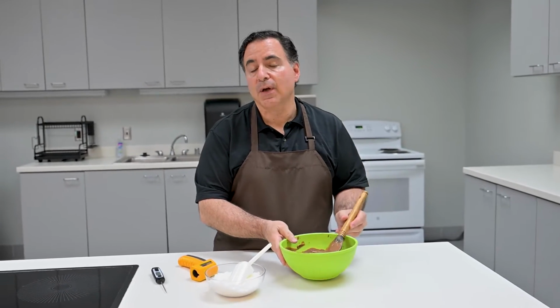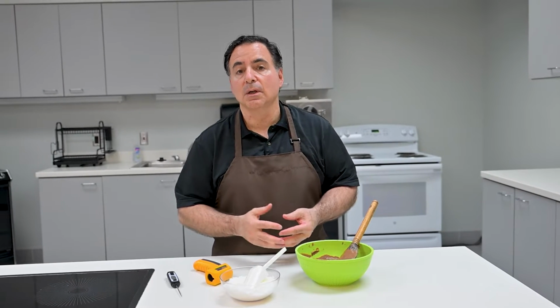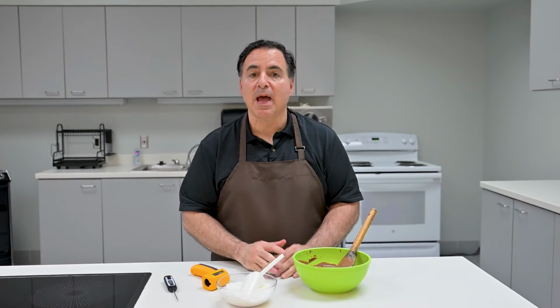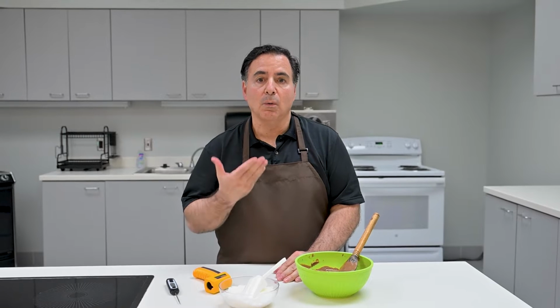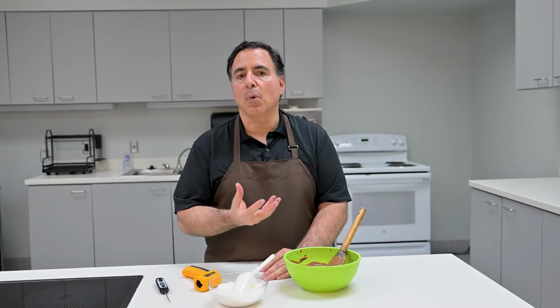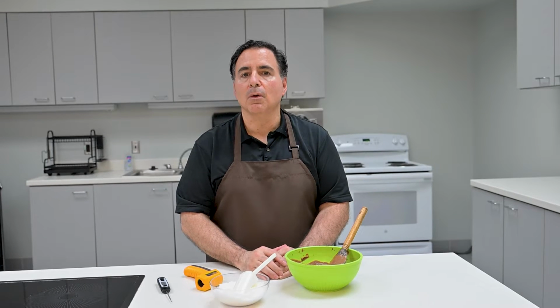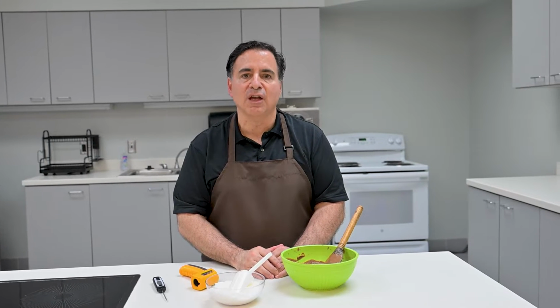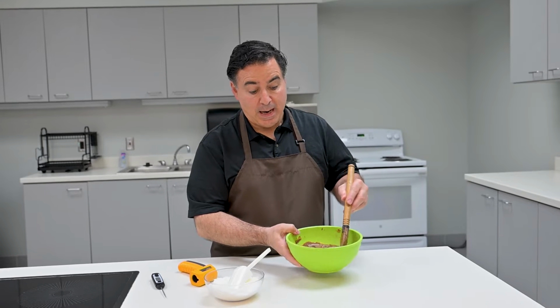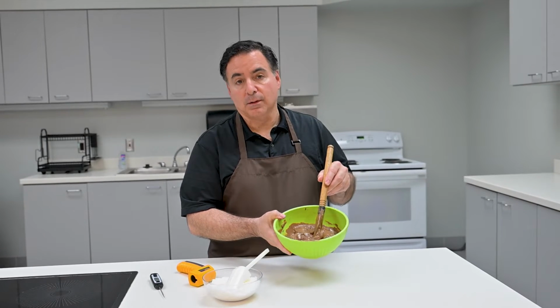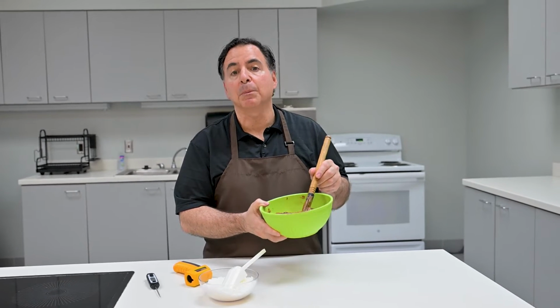What happens with confectionery coating as it ages is that it may absorb moisture from the atmosphere as it gets old. We will see this after 9 to 12 months. So that moisture seeps in to the confectionery coating wafers and it thickens the coating. So if you continue to heat this, you will actually make it worse and you'll probably burn it.